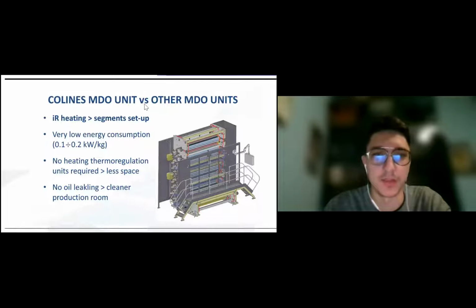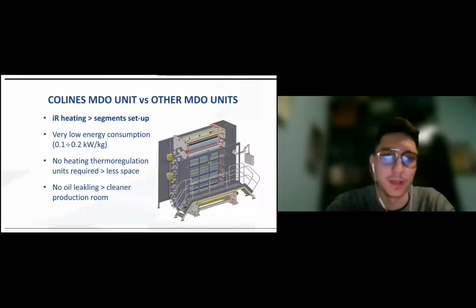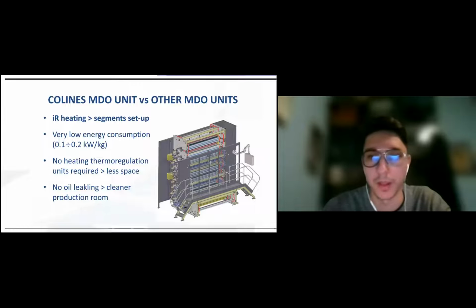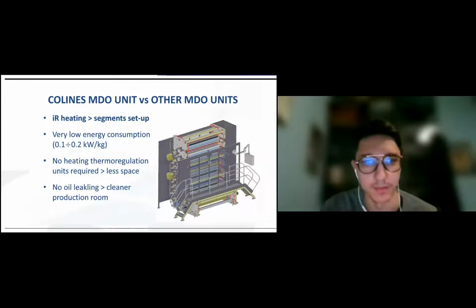What are the advantages of the Colines MDO unit compared to other MDO units? The most important one is the IR heating with IR segments inside of the cylinders. I cannot show you because of our know-how, but inside of this cylinder you have a lot of heating sections with IR segments that you can decide, through your HMI that is placed beside the MDO, how to heat up one single segment or all the segments to give the film the best properties possible. Then we have very low energy consumption because of the IR heating. No thermoregulation unit because it is not an oil or water-based MDO unit. And then no oil leaking because, for sure, you don't have the thermoregulation unit.